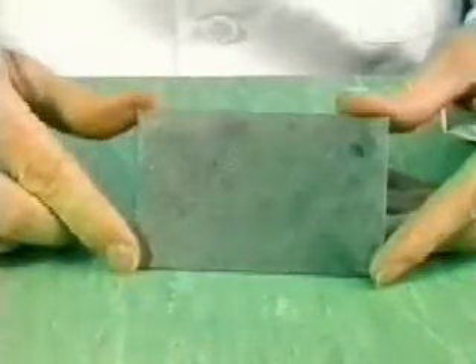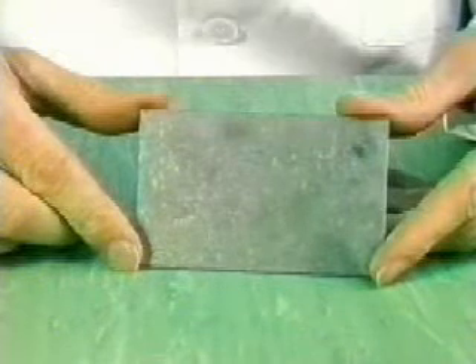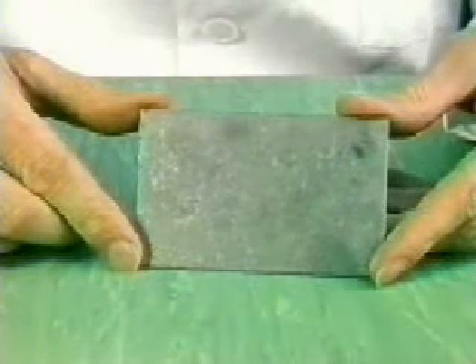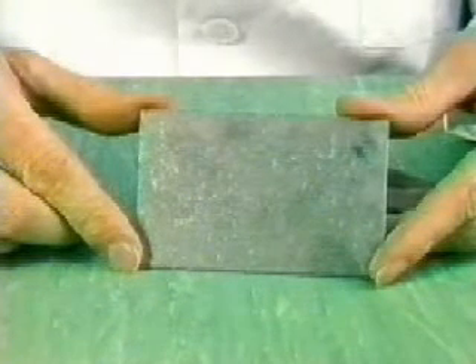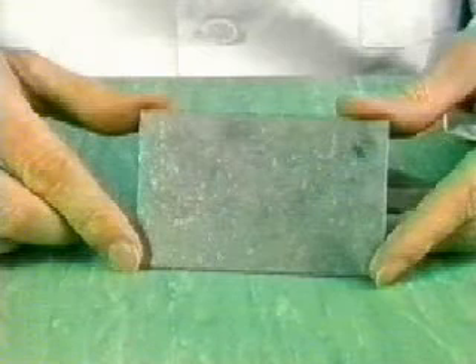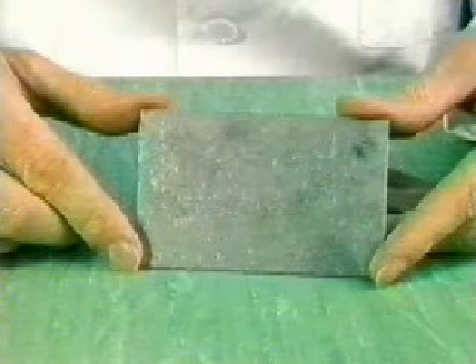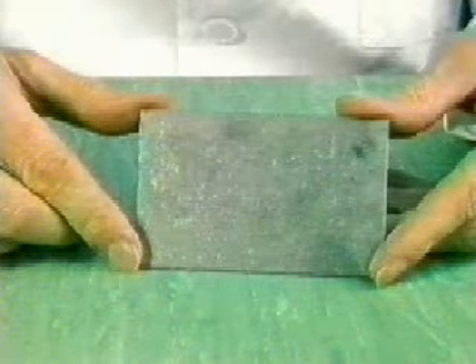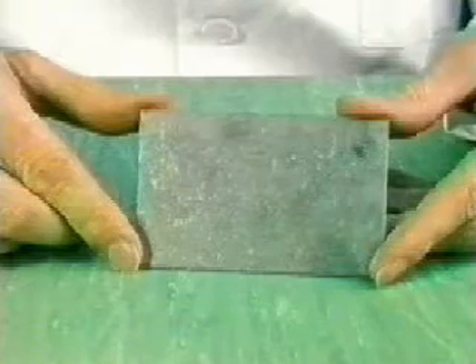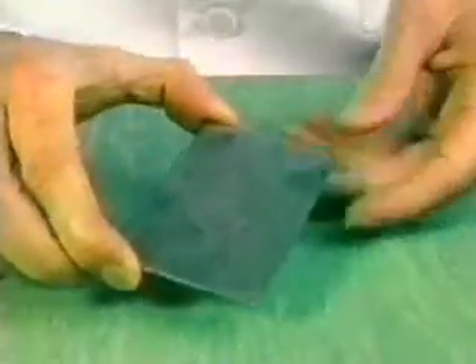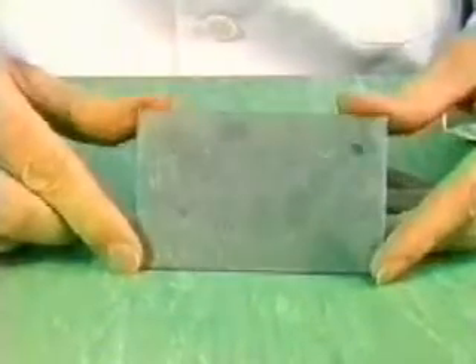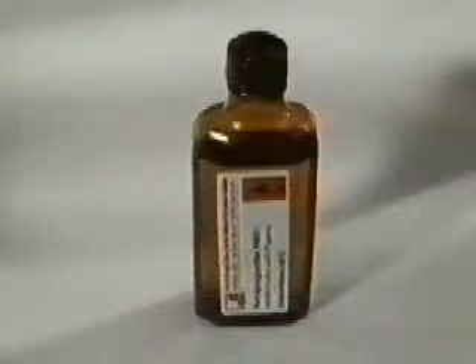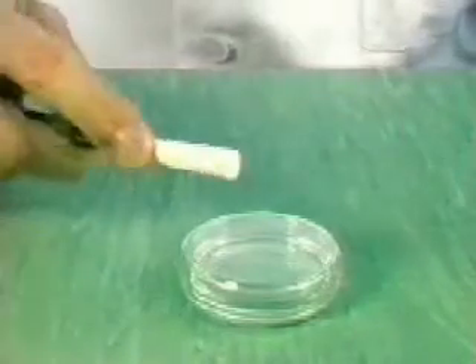Scrapers, spatulas and similar implements are suitable for coarse contaminants. A brush and household cleaning agent can also be of some use on severely contaminated objects. Rust, scale, paint and platings of soft metal, such as zinc, lead or tin, can be removed with grinding equipment. For our test object of bare rolled sheeting, thorough degreasing with a good degreasing agent is sufficient. The solvent must be chemically pure, that is, free from all impurities and from insoluble foreign matter.